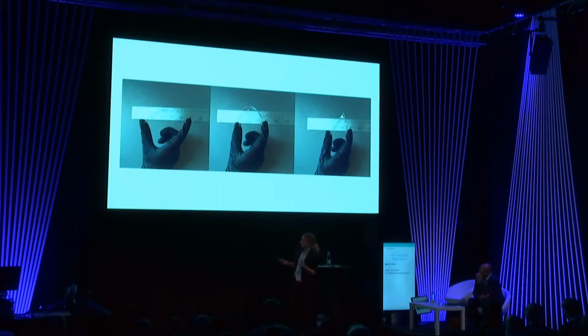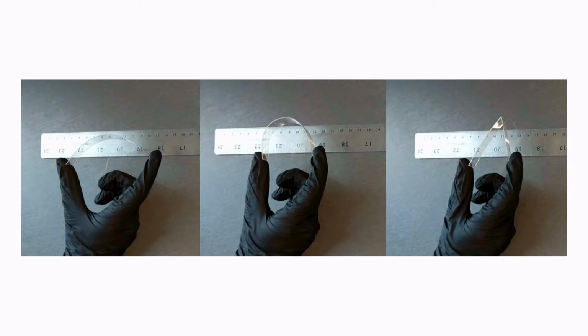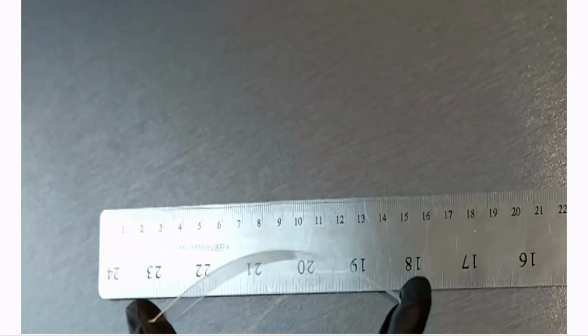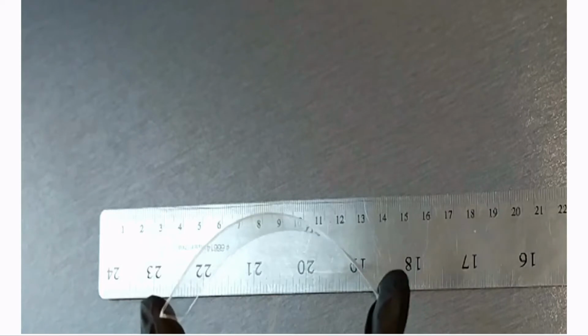What you'll see is basically the first bend state of the laminate, and then we'll see that we have kinks that form on the compression side, about mid-height, mid-span. And then when the tension side broke, this is when it was a complete failure of the laminate. However, the interior kept the pieces together, which was quite interesting. And that's the video. So you see also how much you can bend this material.